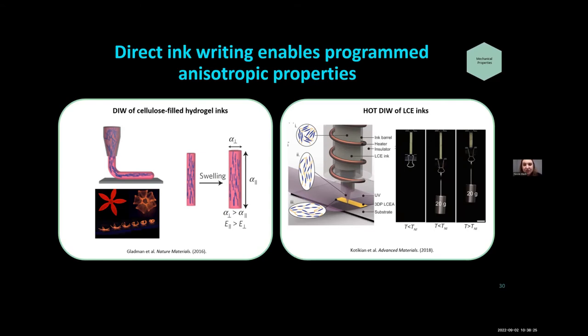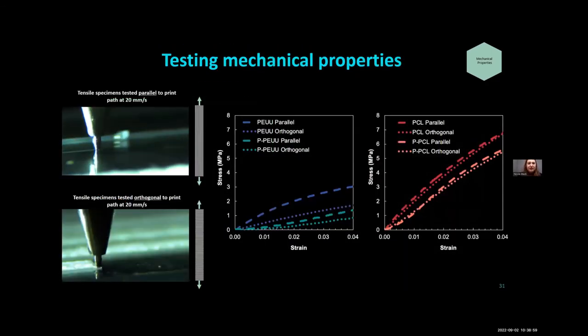On the right is a paper from Arda Kotikian, also in the Lewis lab, who was using hot extrusion printing of liquid crystal elastomers to essentially align these liquid crystal elastomer domains within it, and create these shape-changing soft robotic actuators. So depending on the print path, as these are heated and cooled, you can actually change the shape of these grafts and essentially create these little robotic systems. And so we wanted to do something similar, but with these polyurethane materials.